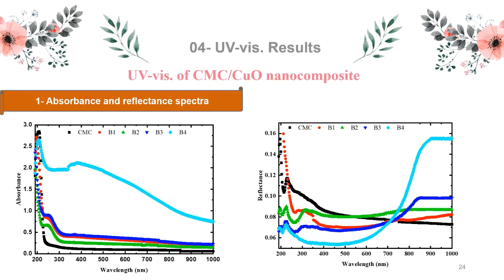UV visible results. This figure presents the dependency of absorption on the wavelength of the incident radiation. As we can see from the figure, there are 2 absorption bands. The first absorption band, located nearly at 200 nanometers, is attributed to the pi-pi star transition of the CMC. Meanwhile, the second absorption band was redshifted with increasing concentration of copper oxide nanoparticles, and this is due to the surface plasmon resonance of the copper oxide nanoparticles. The redshift in the absorption band of copper oxide with increasing copper oxide refers to the decrease in the optical band gap energy.